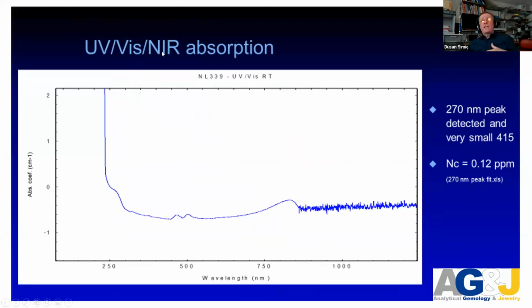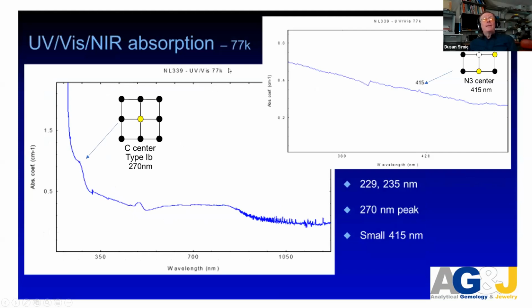In the UV-visible and near-infrared absorption at room temperature, the graph looks perfect for H color aggregation. But if you check this stone at liquid nitrogen temperature, you will see the C center, or single nitrogen, created here, very small, and also some center at 415. Based on this, you cannot make the decision. They are just information that helps you create the whole picture.